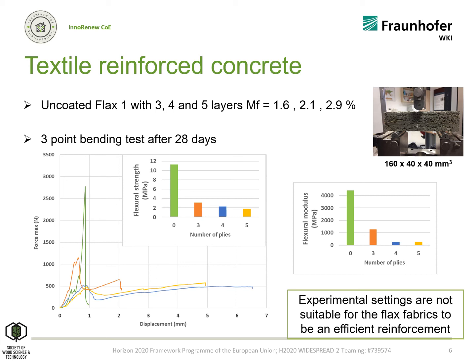We identified at least two issues with the experimental settings. The first one is that the tensile strain of the concrete is very low, so the flax reinforcements are not loaded yet when the samples break at about 1 mm of displacement. So one solution is to impose a pretension of the fabrics during the manufacture of the textile reinforced concrete.